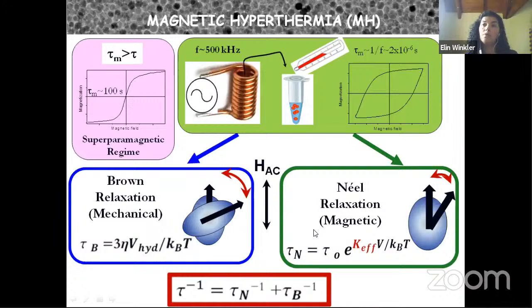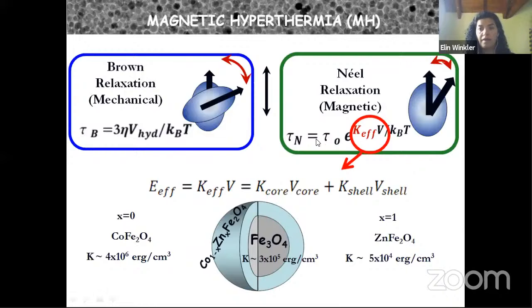So, up to here, we learned that with core shell nanoparticles, we can tune the magnetic anisotropy of the system. So here we have a tool to tune or to move the Néel relaxation time, and if the volume of the nanoparticle does not change, the Brown relaxation will remain unchanged. So that was the idea of this work. And in fact, as the Néel relaxation is an exponential of the anisotropy, it will be very, very sensitive to the anisotropy.